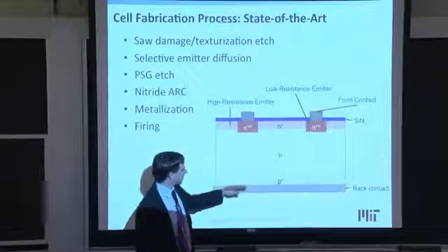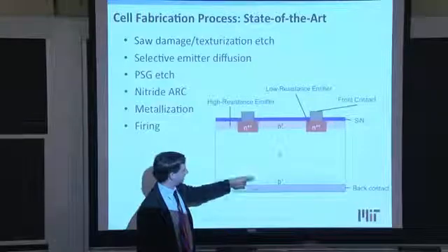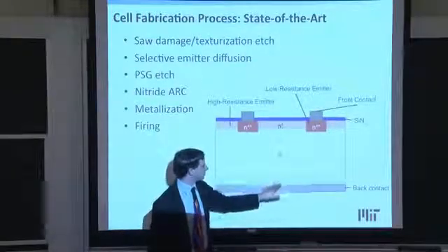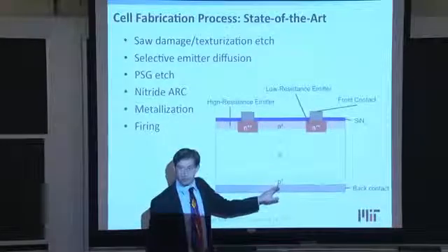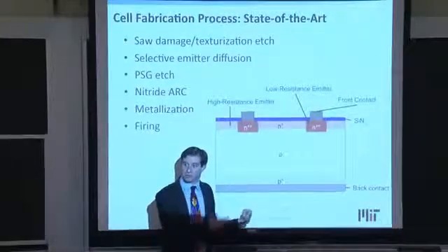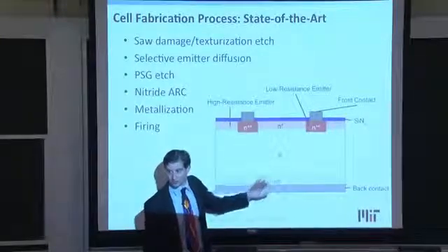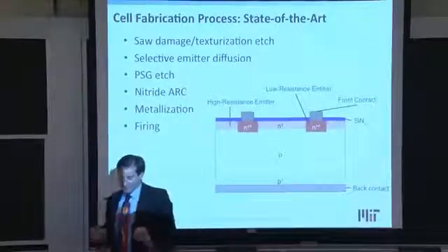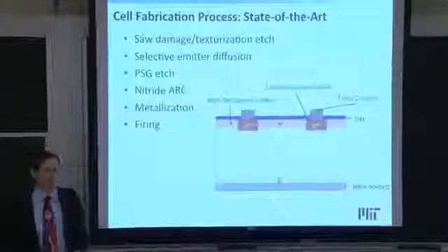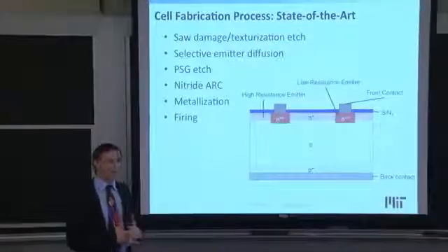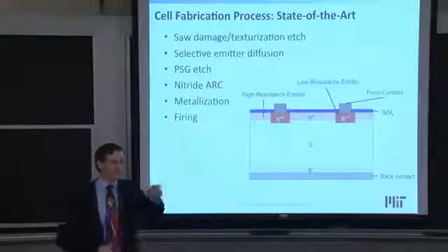Some of the aluminum will indiffuse into the silicon and create a P+ region in the backside here, which is a minority carrier blockade layer. It pushes the electrons away from the back junction and toward the emitter. And so it prevents back surface recombination. So you can see every single little step of the solar cell fabrication. A lot of smart people spend a lot of time thinking about, gee, how do I optimize 2 or 3 things at once?